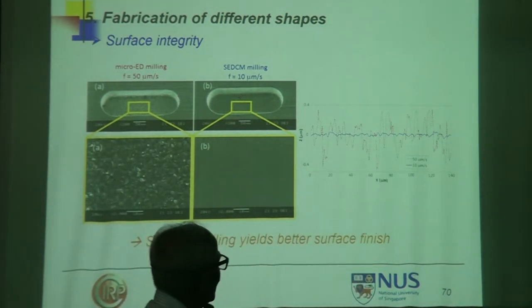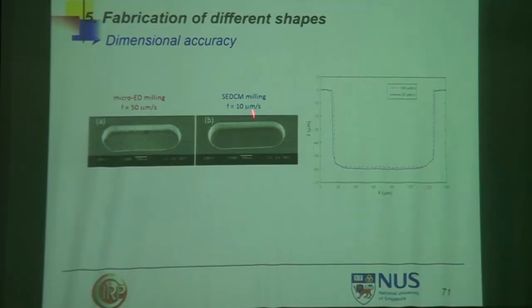The values are not written here. Believe me, the correct value is: red line, surface finish is 142 nano. For the blue line, it is 22 nano. You get a complete mirror surface when you do EDM and ECM together. How come? Okay. And for short pulse and slow speed, you get good dimensional accuracy as you see it. And heat affected zone is removed by electrochemical reaction.